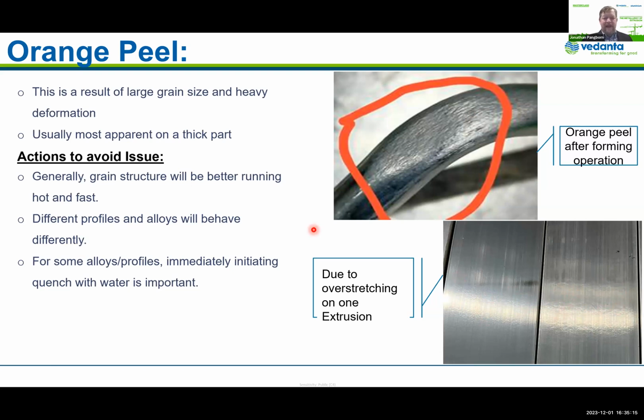Usually this is basically always going to be more prominent on a thick part. If you're running thin wall window frames, you're unlikely to have as much of a problem. It's usually if you have a larger, thicker part. Generally, your grain structure is going to be better running faster and hotter. But again, it's a dynamic situation. There are many kinetic factors contributing to it, so it's not a hard and fast rule. In particular, anyone who's running 6082 often needs to run a colder billet temperature to maintain good grain structure, for example a good minimal recrystallized layer at the surface. But different profiles and different alloys will behave differently.